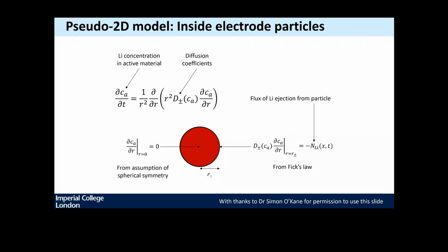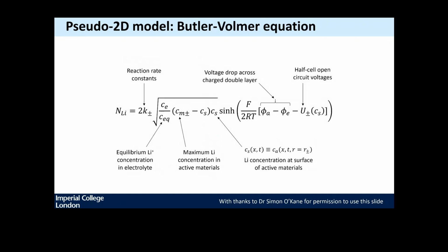It depends on how much lithium is already in the lattice, because that essentially changes the structure of the solid. And so the mobility of further lithium added depends on what the local structure is. These are just two of the parameters you would need to get. They are not all.